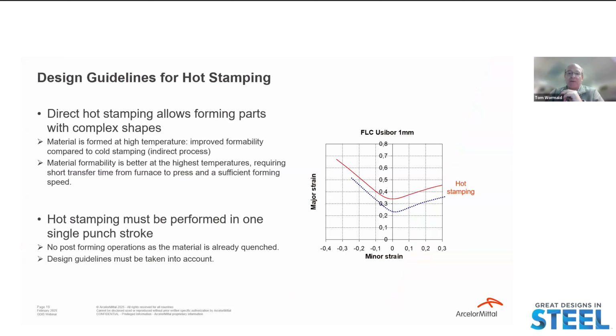When designing parts for the hot stamping process, it's important to understand some of the unique considerations required. Direct hot stamping certainly allows complex shapes to be formed that would not be possible with cold form steels at strengths near those of the finished PHS part. As mentioned, optimum performance is achieved when high temperatures can be maintained for the blank at the beginning of the forming. One important guideline is the fact that the forming is required to occur in a single punch stroke. Particularly for Usibor products, the quenched material is high-strength martensite, and therefore further forming operations should not be considered.